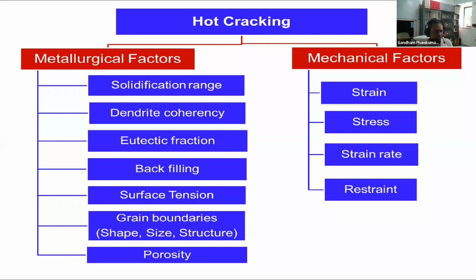Sometimes grain boundaries also play a role. If you have many small grain boundaries, it is good. So a fine microstructure is good when you want to avoid these hot cracks. But if you have coarse grains, and that too with texture, then it could be a problem when it comes to cracking of solidification origin. And of course, porosity can also play a role.